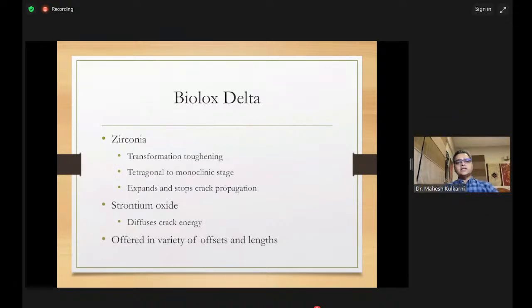And this is what we need to understand with Biolox Delta. You have a combination of zirconia and alumina. Remember, zirconia is not zirconium, or it's not oxidized. Okay, so zirconia is a ceramic. Alumina and zirconia are mixed together. The phase of zirconia itself can actually change its properties when it heats up. It goes through what is called transformation toughening, goes from tetragonal to monoclinic phase. It expands. So if it is mixed with alumina, and if there is a crack which happens in the alumina, the zirconia will expand and block that crack, and it will prevent the crack from propagation.